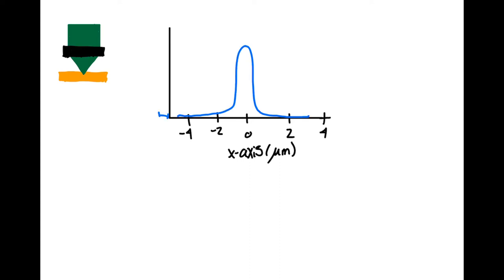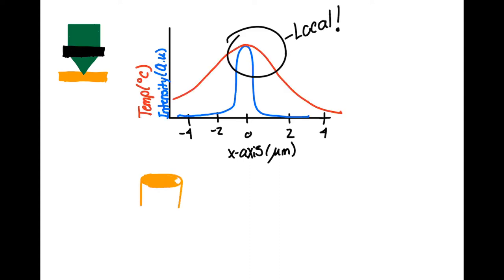In this case, an induced local hotspot is formed on a thin layer of metal which causes the dewetting effect to occur and nanoparticles of size on the order of tens of nanometers are formed.